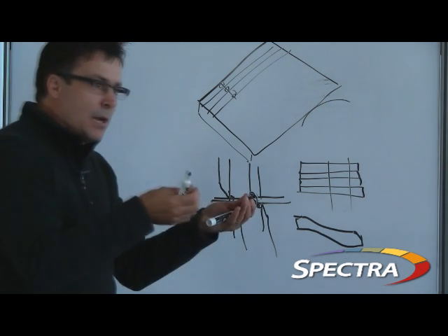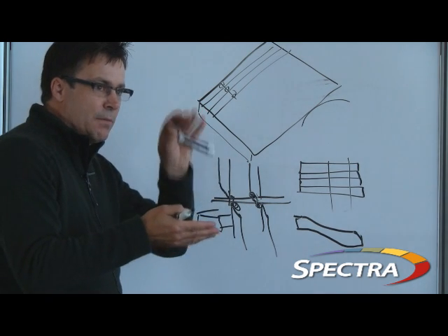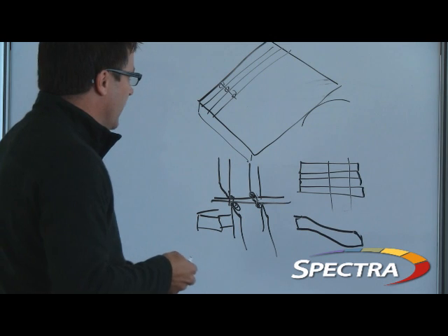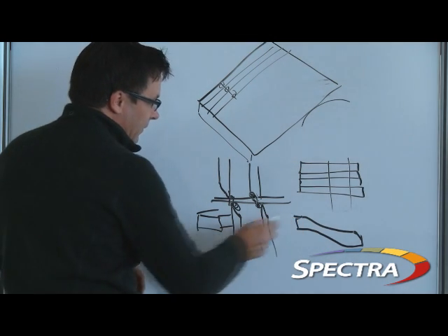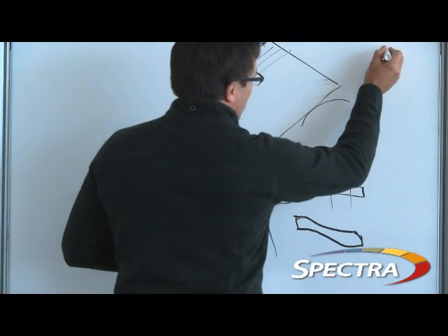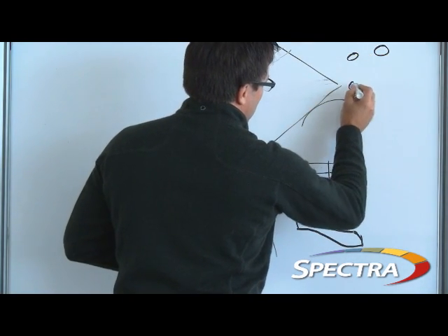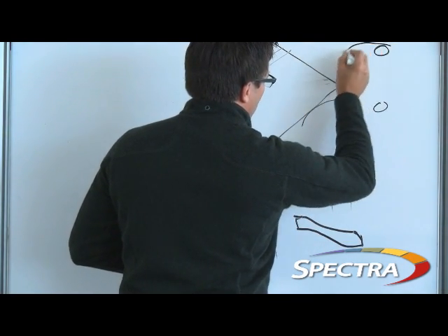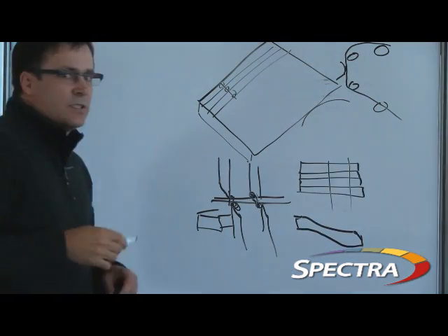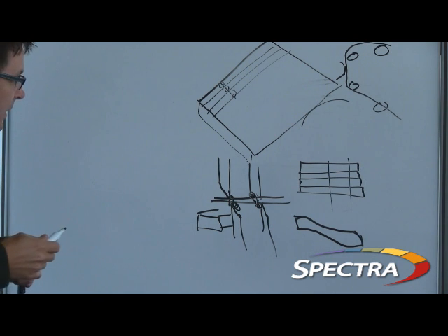But you have a magnetic particle and a magnetic piece of tape, and when they come together, they actually stick quite well. So there's always slitting debris left on the tape. And you have a little deformation in your tape here too. So as the media now comes into a tape drive, you have the capstans, the head, the tape comes by like this and comes out right here. All that slitting debris is going to start building up on the head.